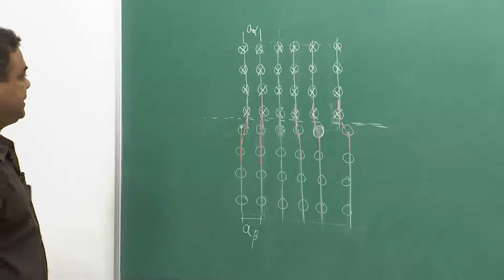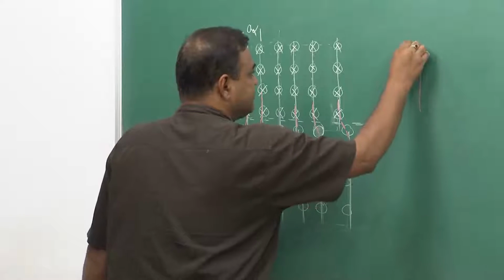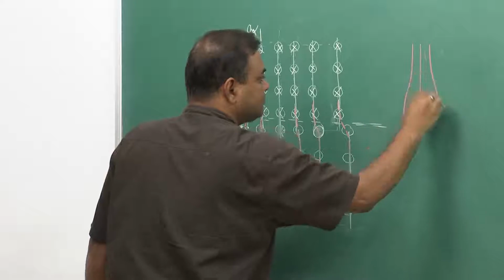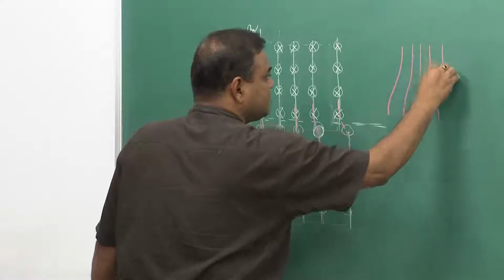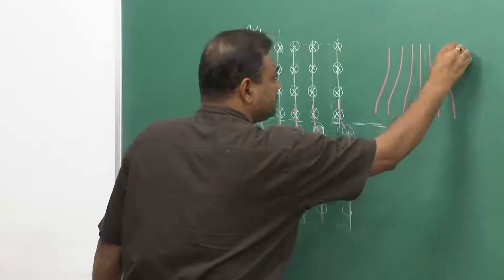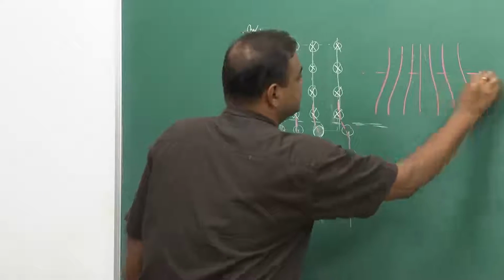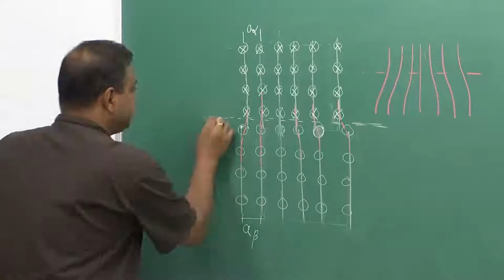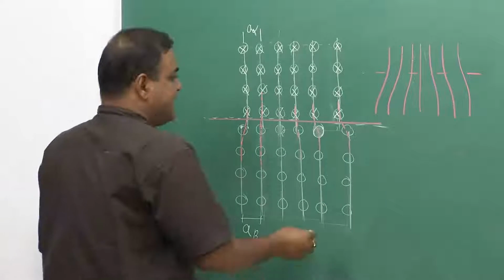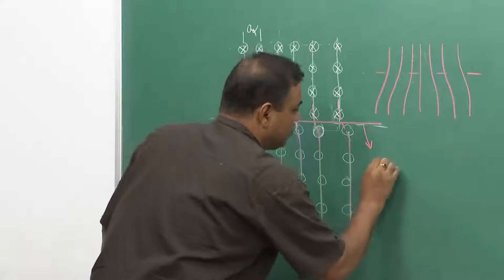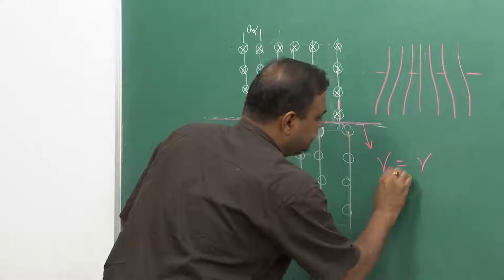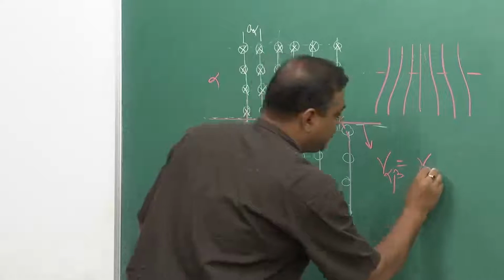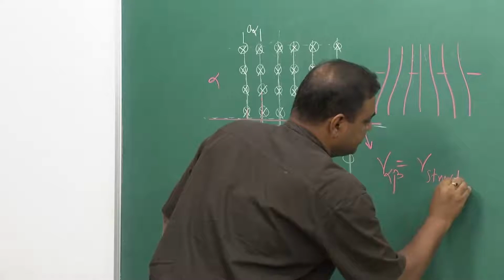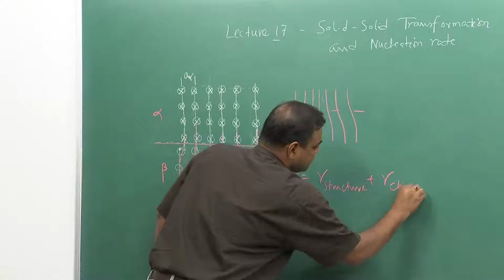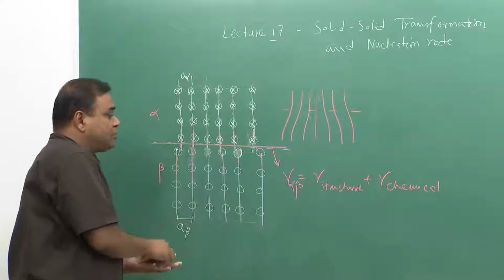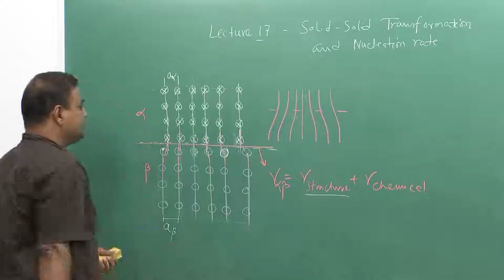So, this distortion would be there. Now you can see that the distortion is like this. So, this is the interface. At that time this interface has two contributions. One is gamma, this is alpha beta, let us say this is beta, this is alpha, gamma structure plus gamma chemical, and out of this, the structure part is related to the lattice distortion.